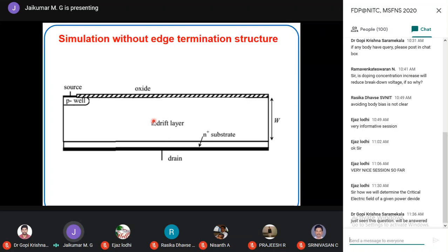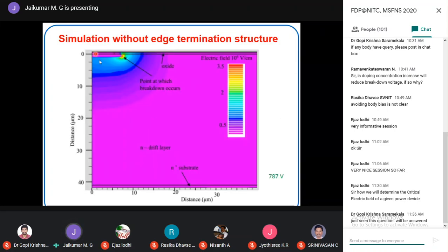It's a typical example only. For a particular structure, we have run a simulation with one of the TCAD simulators available with us. We have simulated the structure without any edge termination. We found that for a 5 kV device, for a plane parallel device, the breakdown voltage was around 5 kilovolts, 5000 volts. Without any edge termination structure, the breakdown voltage was only 787 volts. And we see that this is the area, that yellow or bright red spot, where maximum electric field crowding occurs. And the structure breaks down here.